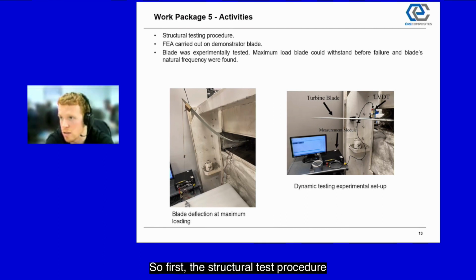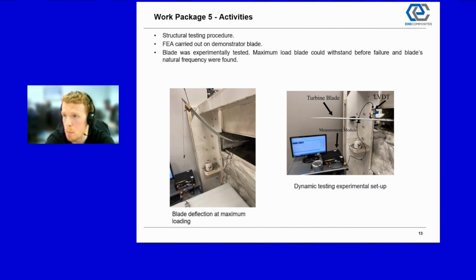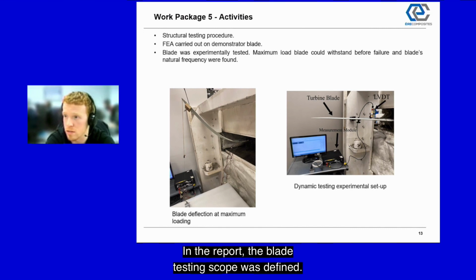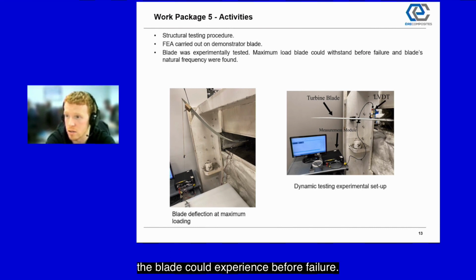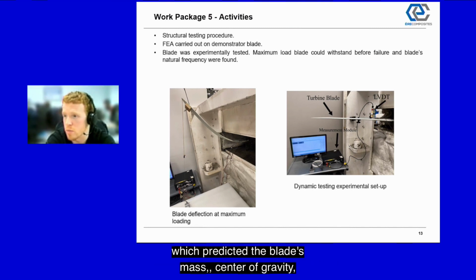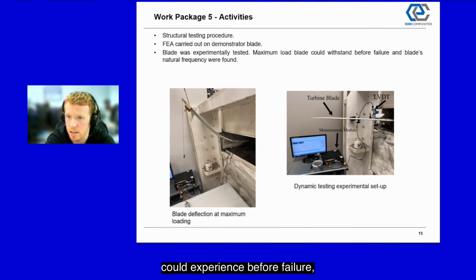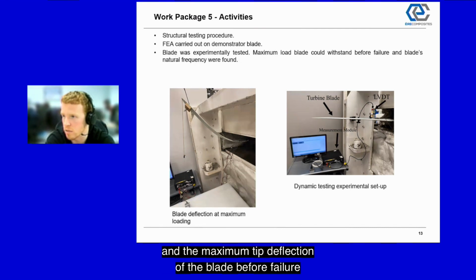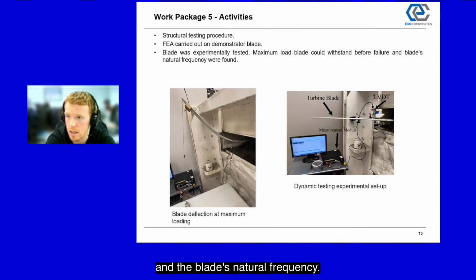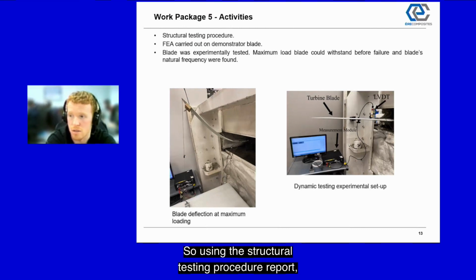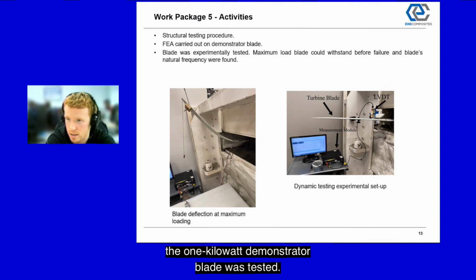So first, the structural test procedure was defined and reported. In the report, the blade testing scope was defined. Predictions were made on the blade's center of gravity and the blade's mass, and theoretical results were outlined for the maximum load the blade could experience before failure. An FEA was also carried out on the blade, which predicted the blade's mass, center of gravity, the maximum load that the blade could experience before failure, the maximum tip deflection of the blade before failure, and the blade's natural frequency.